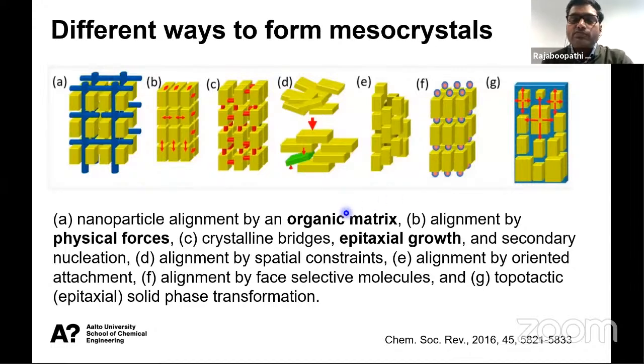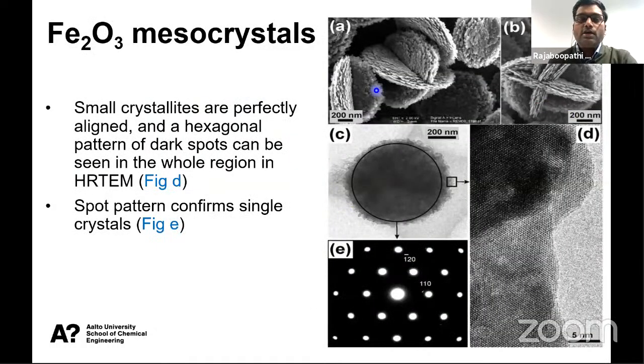Mostly the simple technique is we can use some additives to control the particle attachment. At the same time, we need to maintain some high supersaturation to produce mesocrystals. These are iron oxide mesocrystals, where you can clearly see the mesocrystal structure. When we use this particle for electron diffraction, this is the SAD pattern, where you can see it is a spot pattern. If it is a hierarchical structure, mostly it will produce a ring pattern, but it is a spot pattern. We can say it is a mesocrystal.